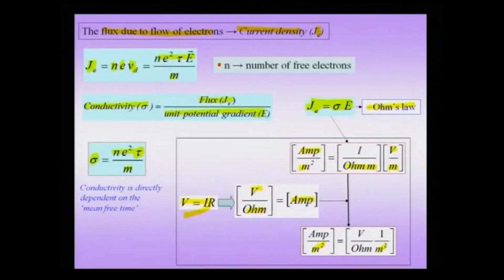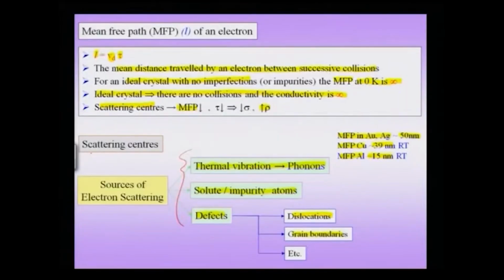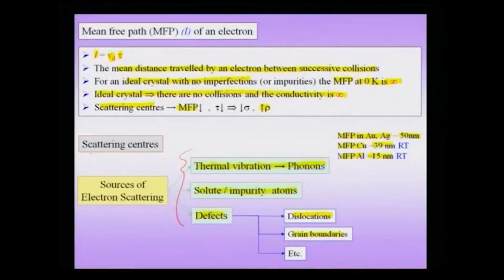In the presence of temperature, this is going to be random motion of electrons. In the presence of an electric field, the electron is accelerated, but suffers collisions, because of which the velocity comes down to 0, and the path it travels freely before a collision is suffered is called the mean free path, and the mean free path or the equivalent mean free time can be related to the conductivity. That means, if you increase the mean free path, then the conductivity increases. Equivalently, note that the mean free path of most good conductors is of the order of tens of nanometers. If I make a nanomaterial or a nanocrystal whose size is of this order, then I would expect some drastic changes in the properties.